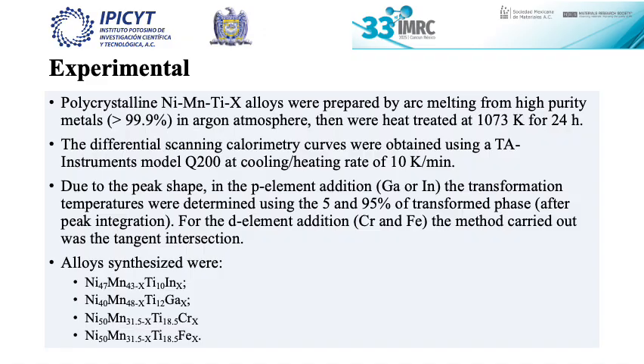So the way to determine the characteristic temperatures were 5 and 95% of transformed phase in two cases, but due to the peak shape for the chromium and iron, we used the tangent intersection. So the alloys were those presented here.